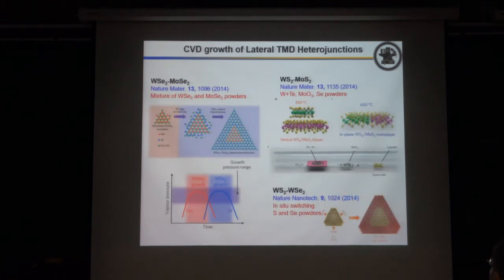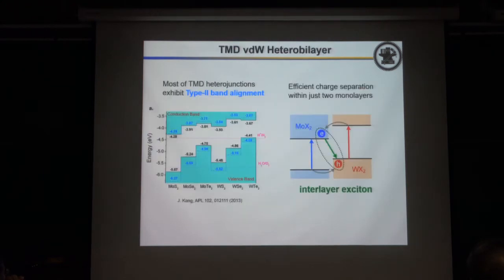So basically, this kind of lateral or vertical heterostructure, you can use different precursor and use different temperature to control. For example, if you use higher growth temperature, you typically will form vertical stacking of different material. But if you use a lower growth temperature, it typically has a lateral heterojunction.